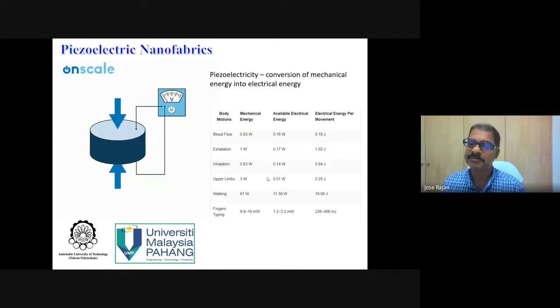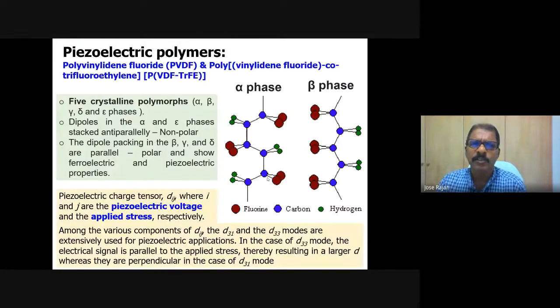In the case of piezoelectric polymers, the most famous one is polyvinylidene fluoride and its copolymer with trifluoroethylene. PVDF has 5 polymorphs: alpha, beta, gamma, delta, and epsilon phases. Among them, the dipoles in the alpha and epsilon phases are stacked anti-parallel, as I have shown in the left image, so that is non-polar. On the other hand, in phases like beta, gamma, and delta, the dipoles are stacked parallel and show ferroelectric and piezoelectric properties. So if we can develop a beta phase of polyvinylidene fluoride, PVDF, and its copolymer, we can have good piezoelectric clothes for our daily use.